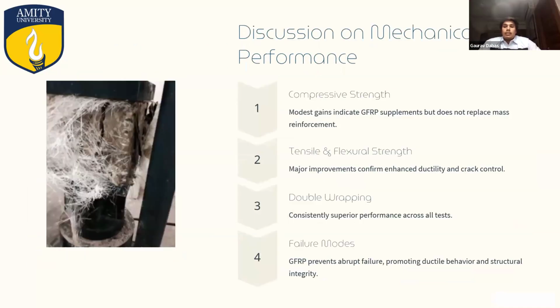Now, the discussion on the mechanical performance of the GFRP. Overall, compressive strength gains were moderate, but tensile and flexural strength saw major improvements, especially in ductility. Double wrapping consistently outperformed single layers. GFRP also shifted the failure mode from brittle to ductile, providing controlled, safer failure behavior.